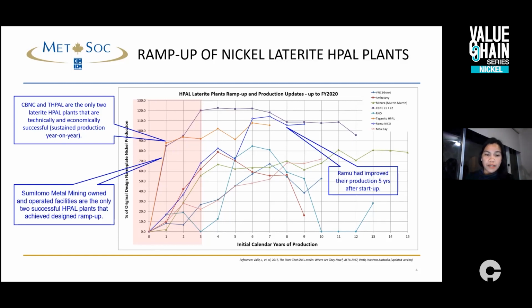I used to work for Coral Bay Line 1. We are one of the pioneer crews in this operation. So Sumitomo started with Line 1 first. And then once we got all the technical de-risking, as well as the skills and knowledge, the company expanded to Line 2. So with Line 2, it was a very fast ramp up because of the acquired skills and knowledge. And it's a strategic capability that really made it. Line 2 ramped up in just 6 months, and they were able to achieve 100% capacity. Not 100% capacity of annualized nickel, but 100% operating capacity.